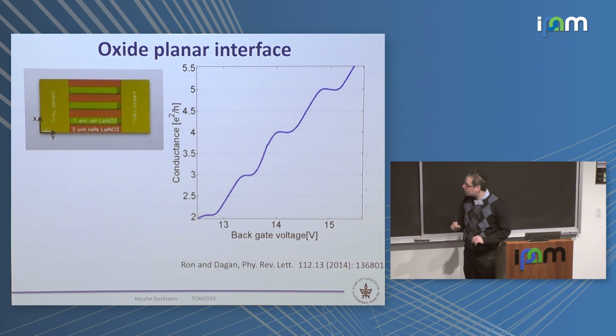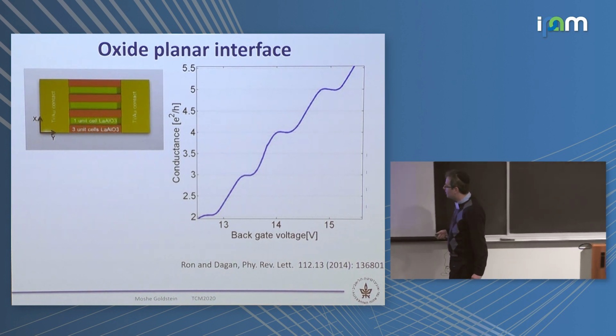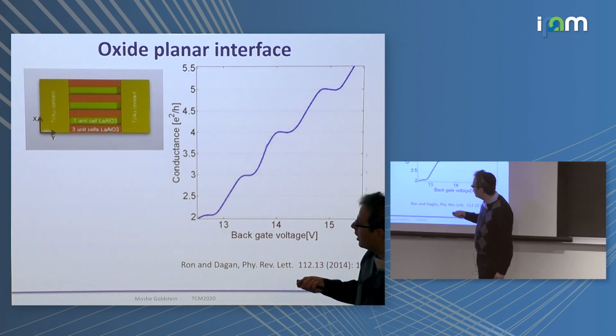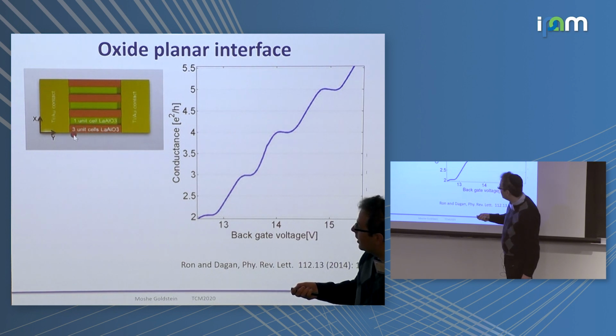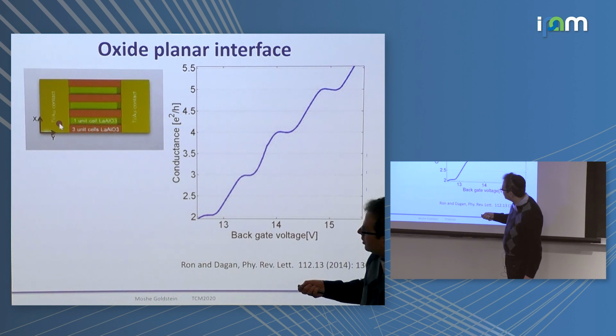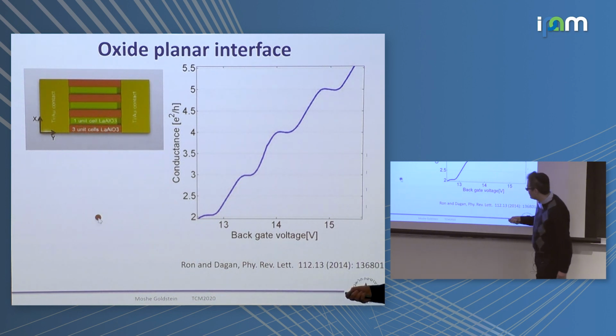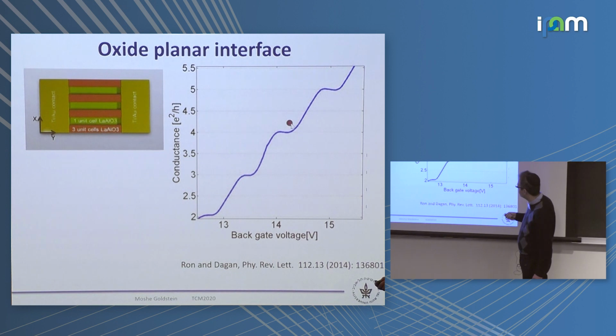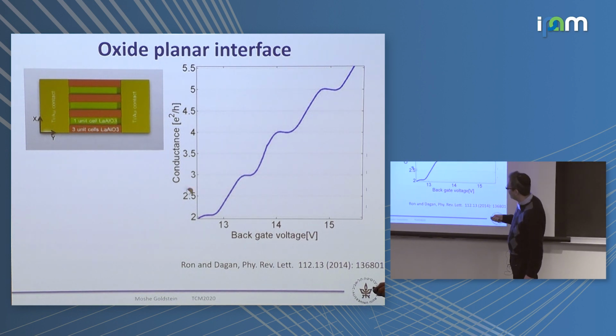Or another thing that you can do, and this was done at Tel Aviv, it turns out that if you have basically a modulation, you go in some regions 3 unit cells of LAO, in some regions 1 unit cell, so each one of them is not conducting, but somehow the 1D interface between them actually does become conducting. Not only it becomes conducting, but at least in some of the devices, you see as function of gate nice conduction steps as function of a gate.